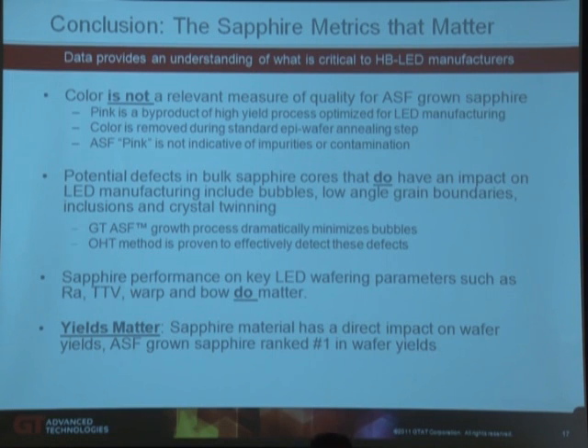Sapphire performance on key LED wafering parameters such as smoothness, total thickness variation, warp, and bow do matter. They do impact the yield of the wafering houses. So the metrics that do matter are yields. Sapphire material has a direct impact on wafer yields, or the profitability of the wafer houses, in other terms. And ASF grown sapphire ranked #1 in wafer yields.